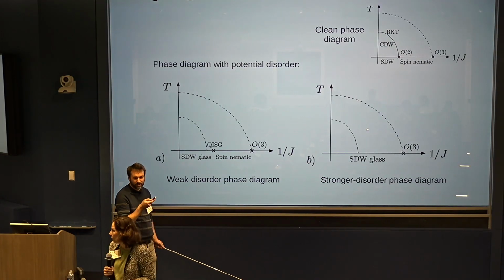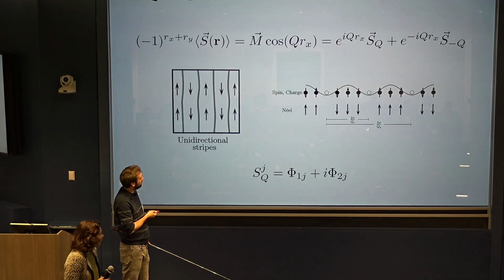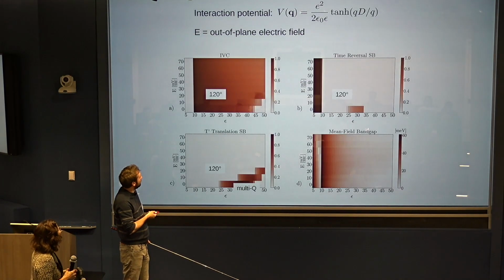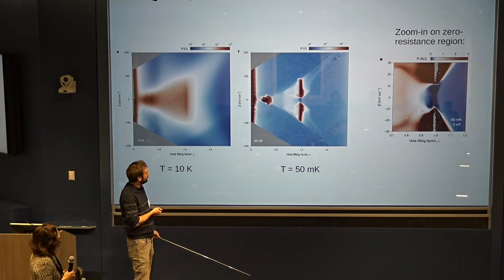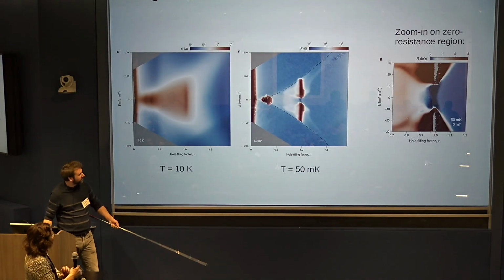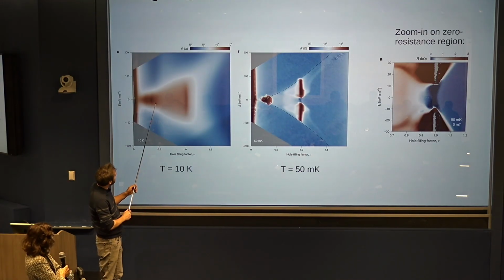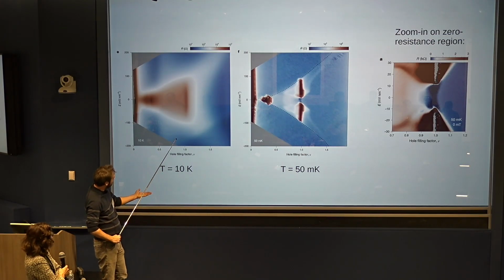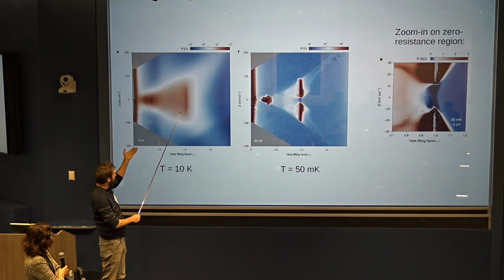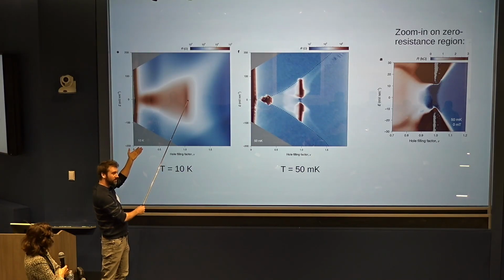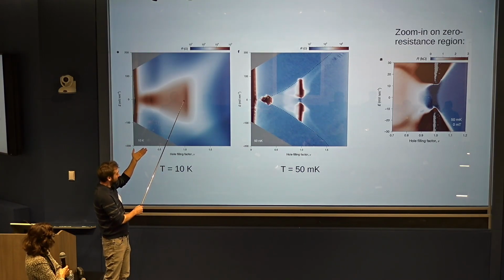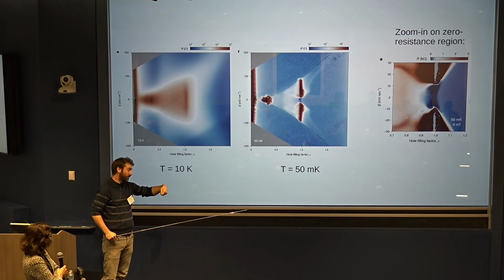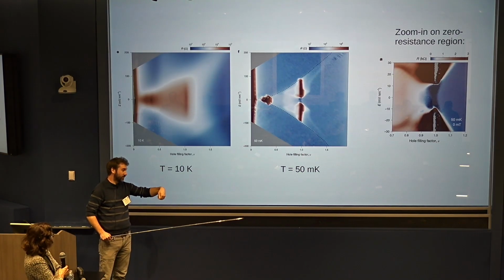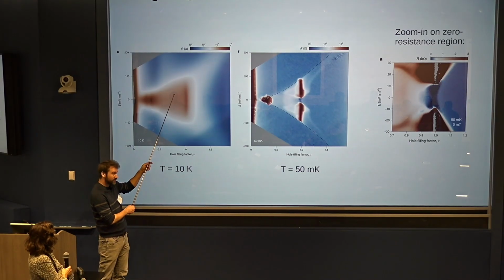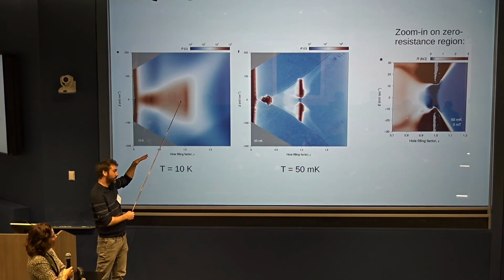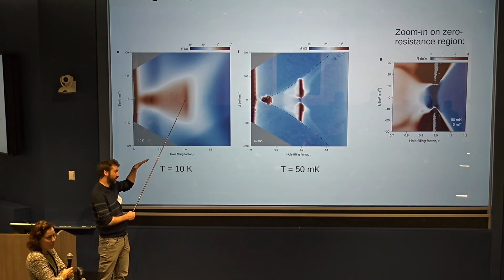And actually, let me first comment on what I think is going on. The multi-Q order is much weaker than the 120-degree AFM. And I think what's happening here, in this high resistance region, as you heat up the system, the multi-Q order would no longer be an instability, even at mean field level. And what you find is that if you suppress the multi-Q order by hand, the system at 0 temperature doesn't become metallic. So I think what's pretty reasonable is that as you heat up the system, and there's no longer an instability to the multi-Q order, you actually find a 120-degree antiferromagnetic metal.